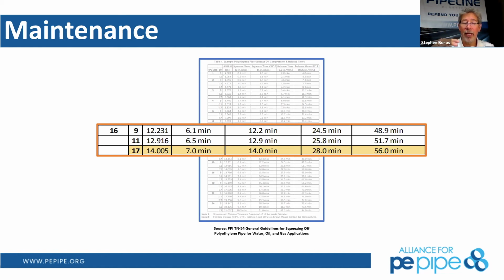And you can see how the release rate is even longer. So in a cold environment, that can take as long as an hour to release that squeeze so you don't damage the product. It's a key benefit, but it's got to be done the right way. And this guide will give you a lot of information about where to go to get the right information on tools and the methodologies and how they're qualified.